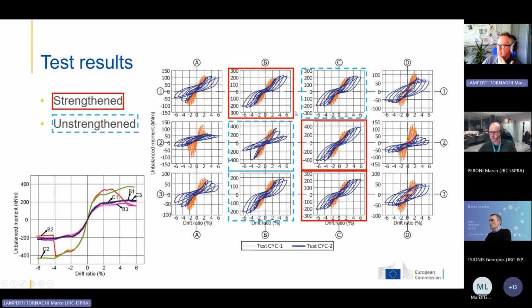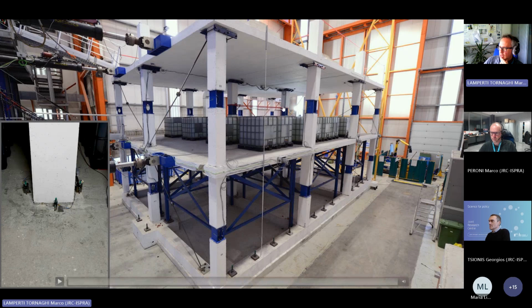This is a brief presentation of the test results. You see here the first cyclic test in orange and the second in blue. You can directly compare the central column unstrengthened, in this case the B2, and strengthened, the C2, and you see here a drop of resistance caused by the punching, and then the second part of the earthquake had a lower stiffness and resistance compared to the strengthened one, which increased the stiffness and the resistance during the earthquake. So this demonstrates that the strengthening was efficient in increasing the resistance of a building not designed for earthquake areas.